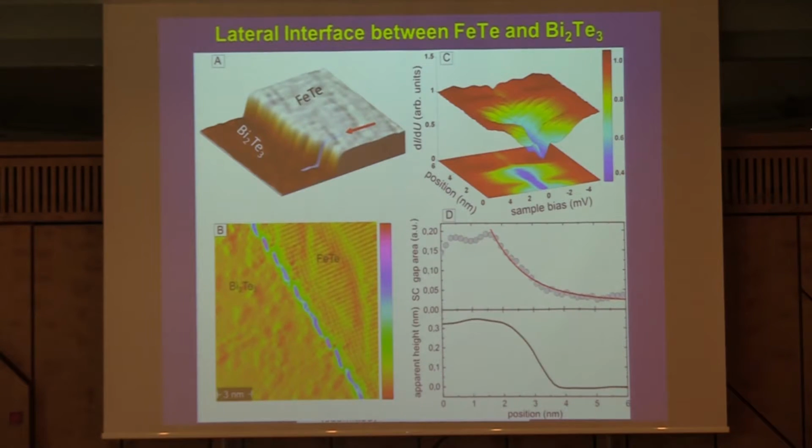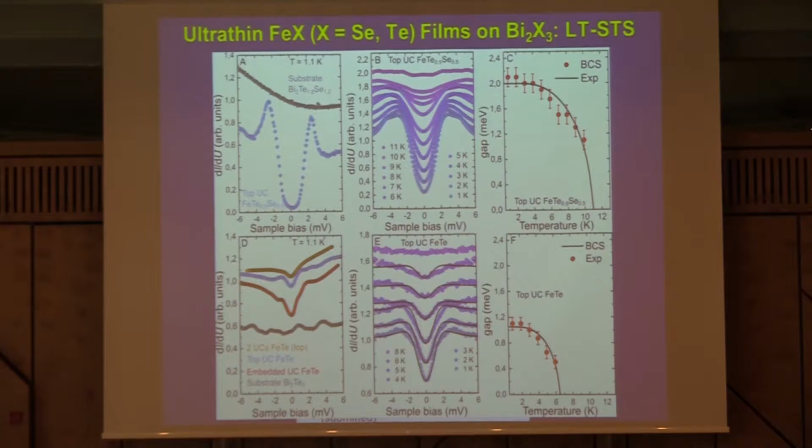Now, we did very careful studies of the temperature, field dependencies, and so on. And the interesting point is that this gap feature, which we observe for the iron tellurium, basically starts to disappear already here if we go to 2 and even 3 unit cell thick layers.